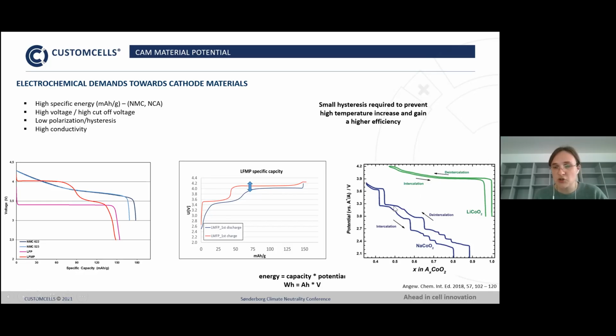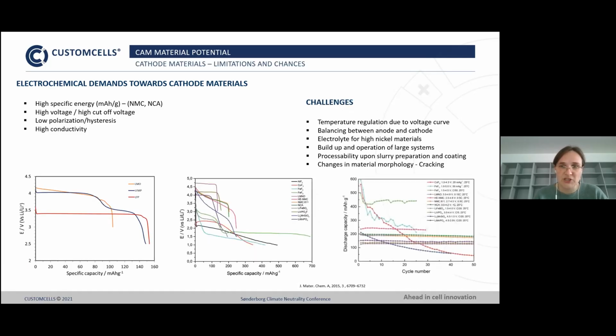And here a very recent trend is the sodium counterpart of the lithium-ion battery. Here we have a very nice comparison between the lithium cobalt oxide and the polarization here. And for example, the sodium cobalt oxide, where you see that there are many steps upon charging and discharging, and there's also a higher polarization, and therefore thermal energy is lost. You always have to take this into account when you are deciding on a battery type. I will not go too much into detail here, just maybe as a takeaway message.